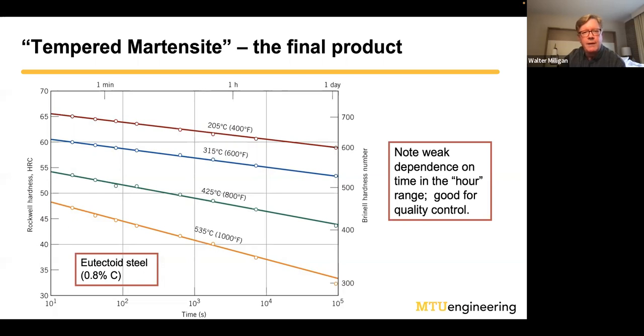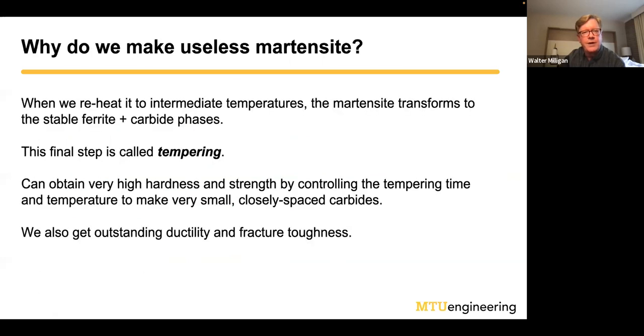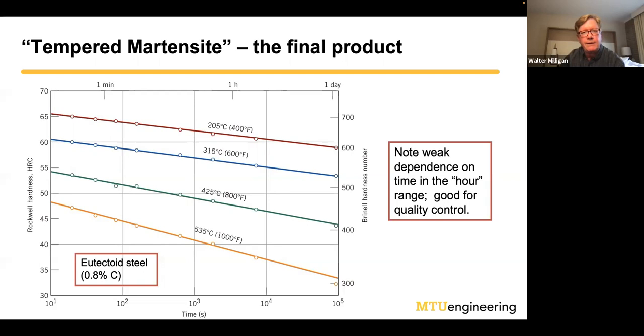So once again, the 3 steps that we have to do here are we have to heat it up to the high temperature austenite. We quench it to form martensite, and then after we form the martensite, we got to get rid of it. And so we temper it for an amount of time, and the result of that microstructure is called tempered martensite, even though there's no martensite there. And that drives students crazy in the intro class that I teach, because it's called tempered martensite and there's no martensite there. We called it tempered martensite because that's how we made it.